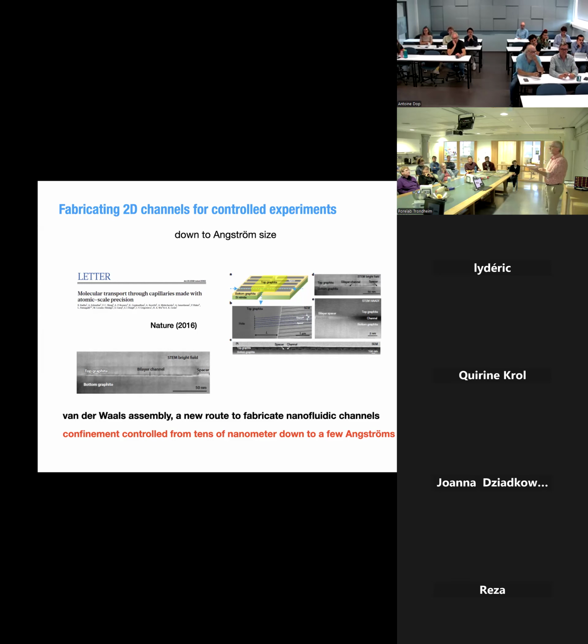But then once you have a graphene, which is 1, 2, 3, or 1,000 layers, I mean, it's not graphene anymore, but you can mill it, so take out some parts, and put it on graphite. And then if you put it on graphite, you can put, again, a top graphite on top of it, another sticker. And by assembling this, you do a channel where the thickness is fixed by the number of graphene layers that you have. So you can really go down to 3 angstroms, actually, in size, and in a very controlled way.